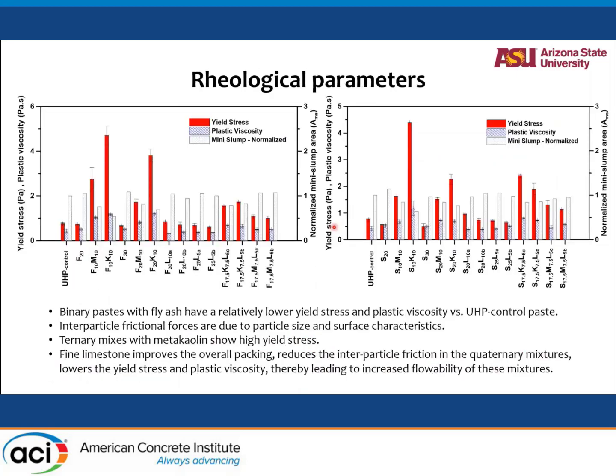So in terms of rheology, we started with simple rheological tests, parallel plate rheology, calculating yield stress and plastic viscosity. After that we have done vane shear also, and these results are vane shear results, actually, not parallel. So we did yield stress and plastic viscosity and also mini slump because we want to find an easy way to quantify what our spread is while we were doing the rheological measurements.